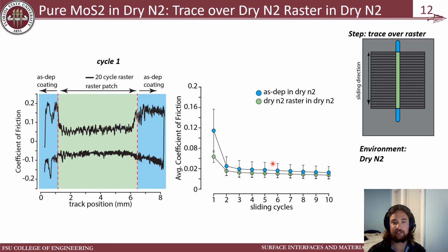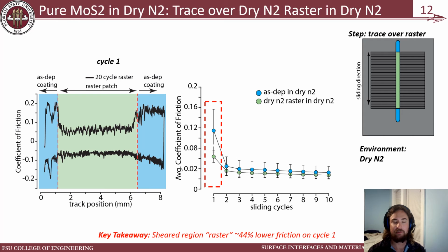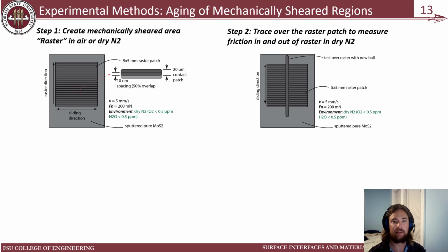So the key takeaway here is that a sheared region is much lower friction than an as deposited coating, as much as 44%. Now that we have tested the MoS2 coating before oxidation in steps one and two, as we just showed,